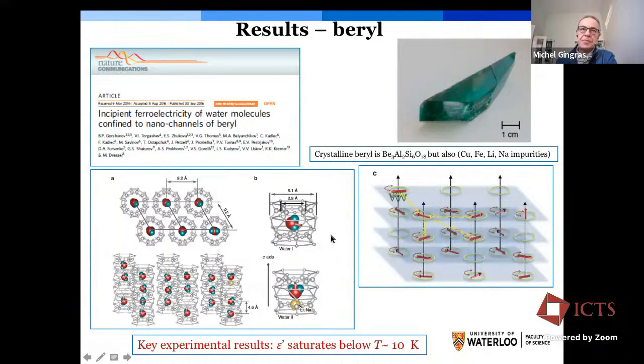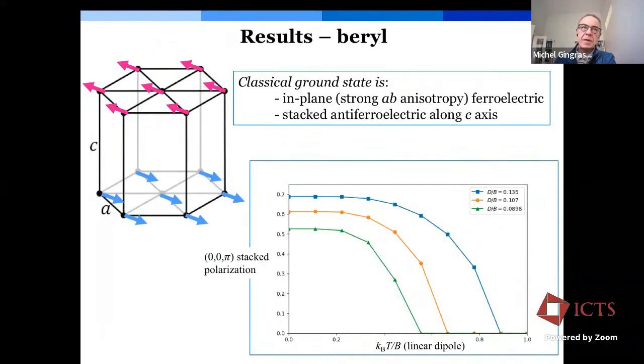And so the question is, what happens in that system? There is evidence that there is a saturation of the dielectric permittivity in the systems below 10 Kelvin. But again, we ask, where are we in terms of phase diagram, possible phases for encapsulated water in such systems? So let me immediately jump to the results. And so what we find is that the semi-classical ground state in these systems is interesting.